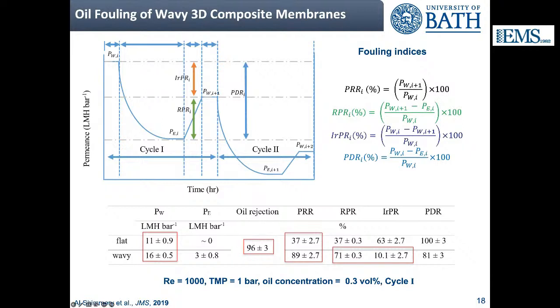You can see that they have the same rejection because this is given by the PS layer. But what is interesting is that the recovery of the permeance for the wavy membrane is 71%, whereas for the flat membrane it's only 37%. And the reversible fouling is 10% for the wavy membrane, but 63% for the flat membrane. So this is very clear evidence that the wavy structure not only slows down the accumulation of fouling, but makes it easier to dislodge the fouling that has formed. Some fouling will form anyway, that's just inevitable, but the wavy structure slows down the accumulation of fouling and makes it easier to dislodge once the fouling layer has formed.